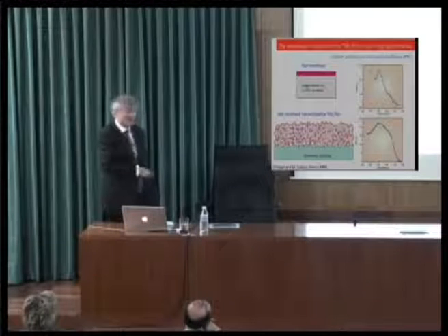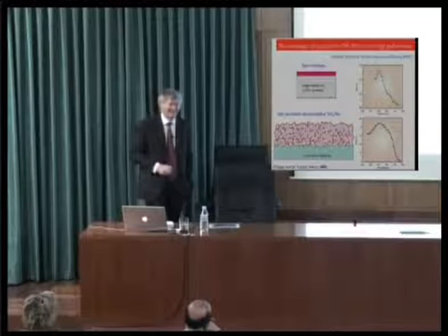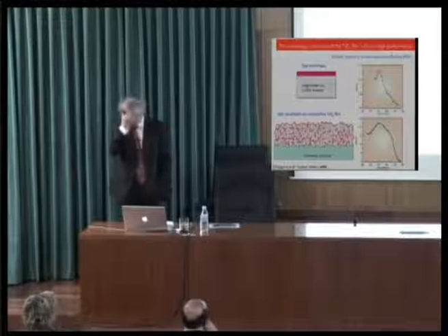But when we use these nanocrystalline films, you see the dye now gets a 3-dimensional junction. And this is the trick, because when the light comes in, it will hit the first particle. Well, a little bit gets absorbed. It hits the next, and it goes through hundreds of particles. And finally, you get the light captured. And every time the light is absorbed, you generate electrons in these particles. And so at the end, I get over 80% conversion of photons to electrons, in the spectral range where we have a good light absorption of the dye.